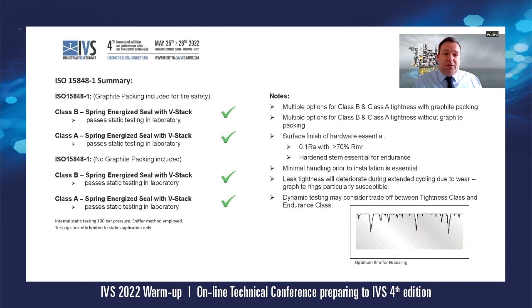Firstly, the surface finish is incredibly important for achieving lowest possible leakage rates. Our best results were achieved when we polished our stem and groove walls to 0.1 RA and achieved a bearing ratio in excess of 70%, as shown on the slide here at the bottom, with the optimum RMR and lots of valleys in the surface finish and no peaks.